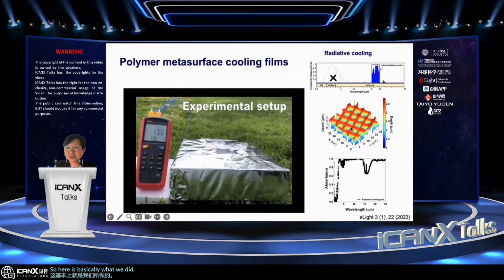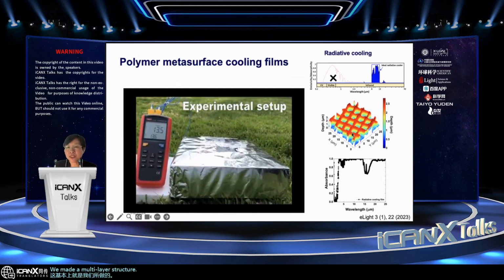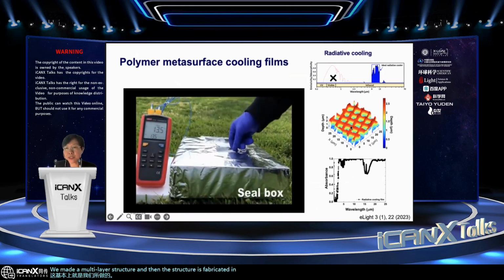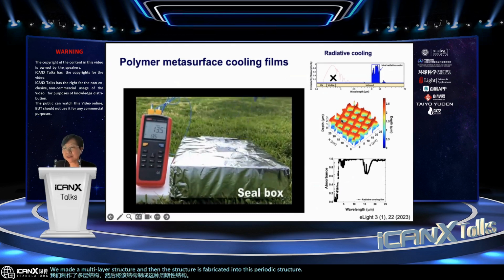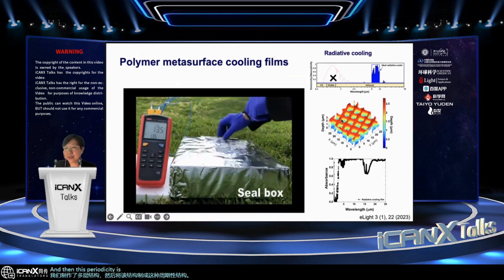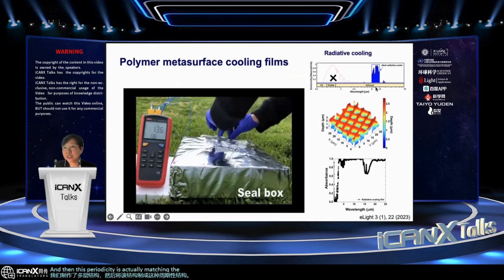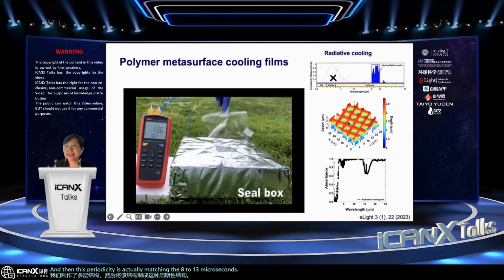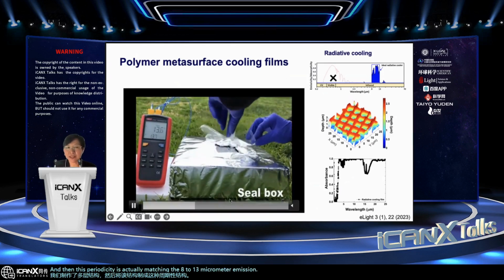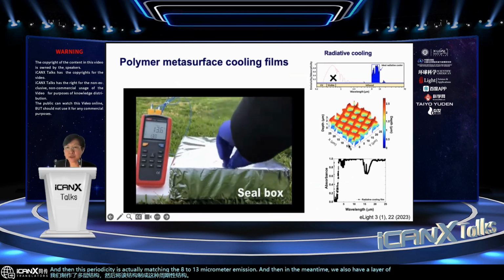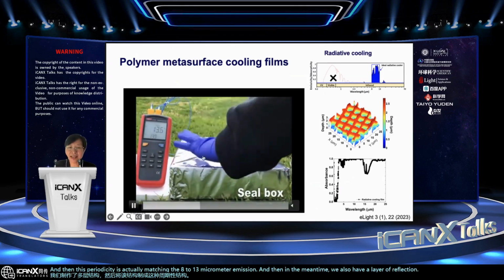We made a multi-layer structure, and then the structure is fabricated into this periodic structure. This periodicity actually matches the 8 to 13 micrometer emission. And in the meantime, we also have a layer of reflection to avoid the sunlight.